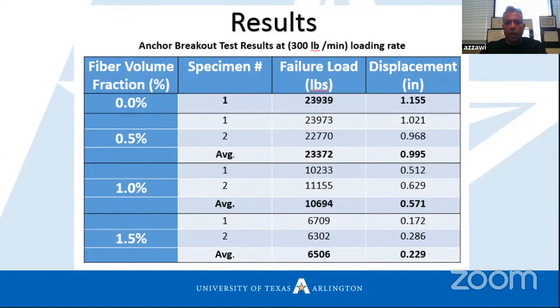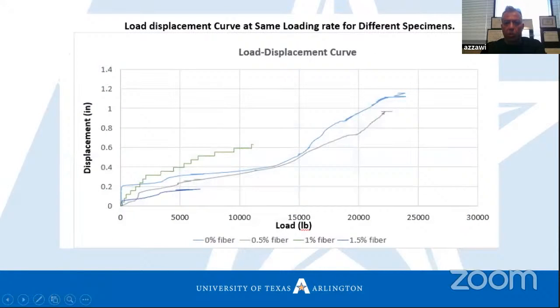This test is done by applying a 300 pound per minute loading rate. So it takes some time to finish the test, and this curve shows us the results. This is the load displacement curve. As we see here, increasing the fiber will decrease the displacement here. That's what we have.